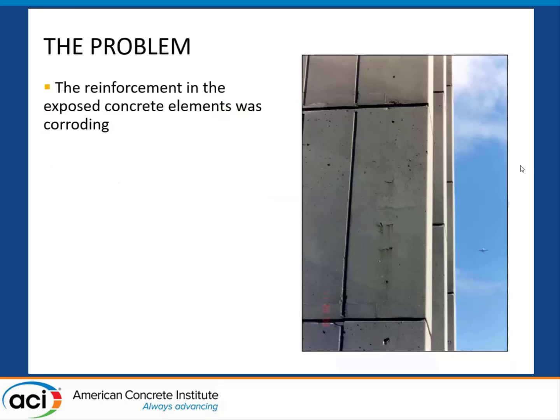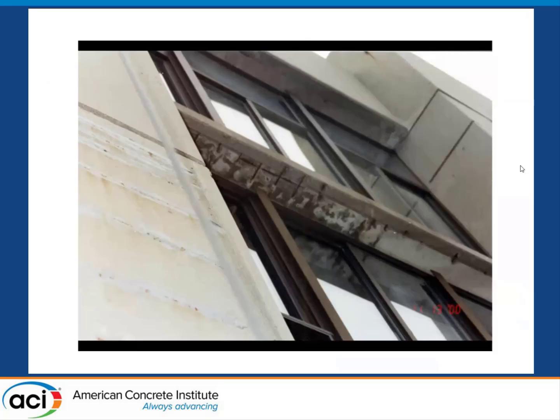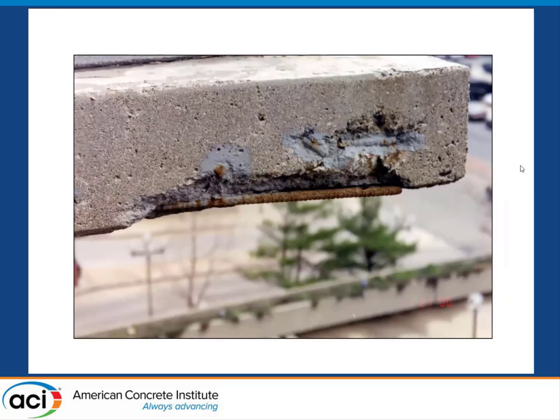So the problem after all that investigation was that there were many locations that had spalled concrete, and it was due to steel corrosion. Here's an example of an underside of a slab near the window wall. You'll note significant spalling there, as well as staining on the wall itself to the left, where the reinforcement was close to the surface and corrosion was occurring there as well. Here is an example of a balcony undergoing some corrosion problems, and you can note there was a previous unsuccessful attempt to at least abate or slow down some of the corrosion by simply painting the exposed reinforcing steel. That was not effective, just a stopgap attempt at trying to do something as the owner pondered what they were going to do.